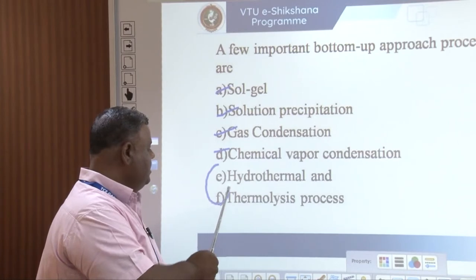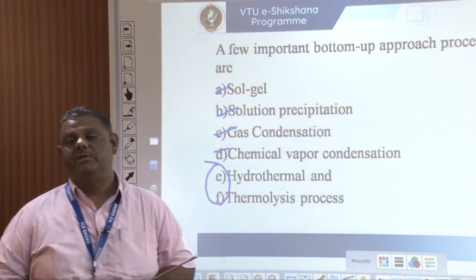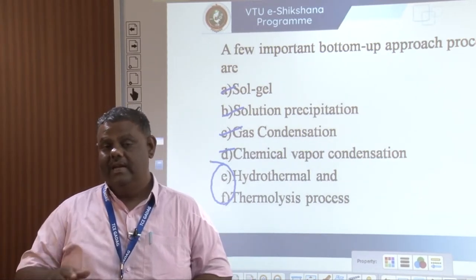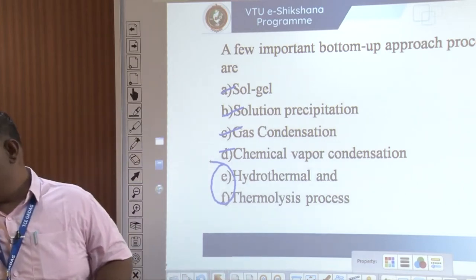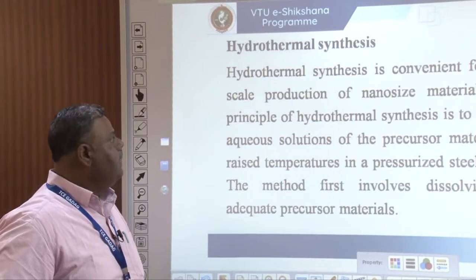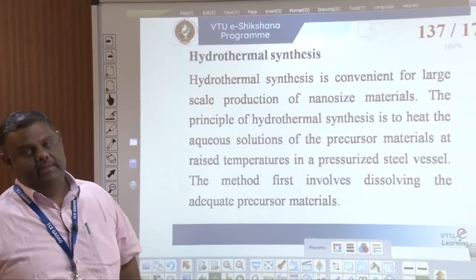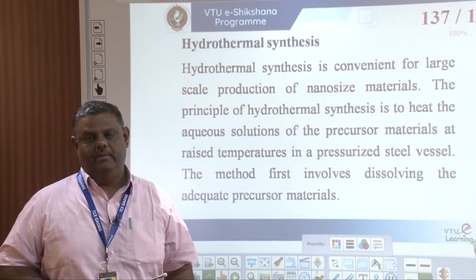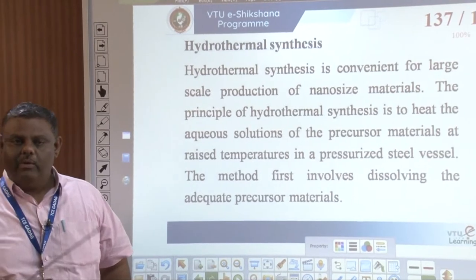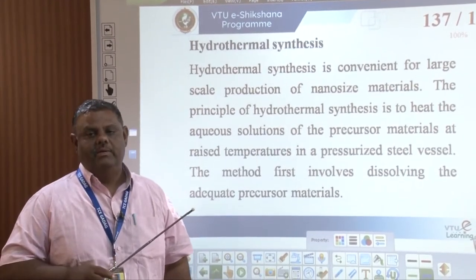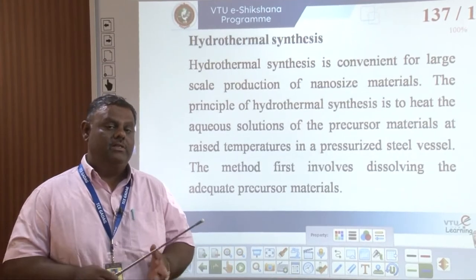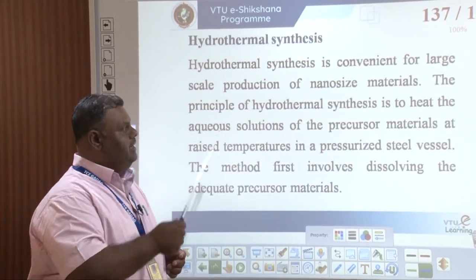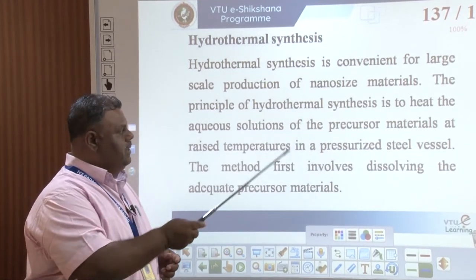We are now remaining with the hydrothermal process and the thermolysis process for the preparation of nanomaterials. Hydrothermal synthesis — as the name suggests — involves heating water. This synthesis is very convenient for the large-scale production of nano-sized materials, particularly for industrial purposes. The principle is that the precursor has to be dissolved in an aqueous medium and heated around 300°C in an autoclave.